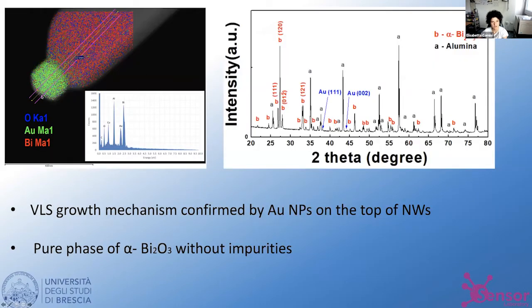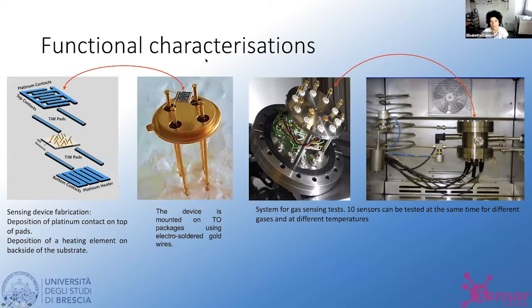You can also see here the EDX spectra, where we can see that the tip of the nanowire is gold, while we have bismuth oxide in the upper part. We have the alpha phase of bismuth oxide, and we can see also the crystalline phase of gold at the top of the nanowires. So now let's see what we are doing with this metal oxide.